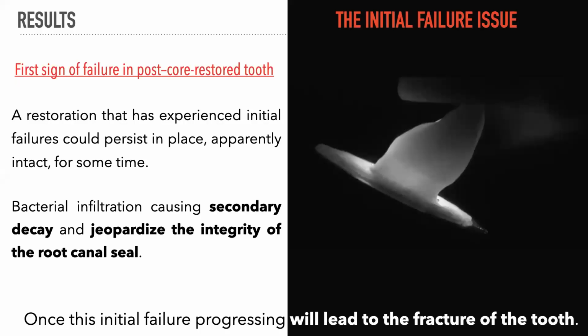So in this study, we learned about this initial failure in the adhesive crowns using glass fiber posts. And these initial failures were the first sign of a failure in a post and core restored tooth. The restoration that has experienced initial failures could persist in place, apparently intact for some time, but we can have a bacterial infiltration causing secondary decay and jeopardizing the integrity of the root canal seal. So once this initial failure progresses, it will lead to the fracture of the tooth.